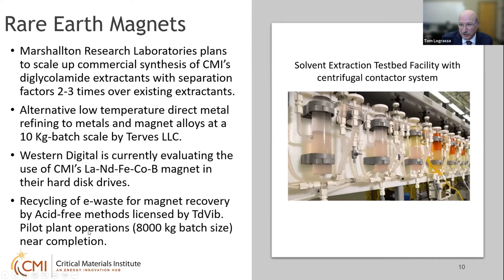And finally, as I mentioned, the acid-free method has actually been licensed by a local company here in Iowa. They're putting the finishing touches on a pilot plant operation, about 8,000 kilogram batch size. So this is taking mostly hard drives, which are crushed and shredded for data security reasons. And this acid-free method, very selective, goes in and just removes the rare earth, anything rare earth dissolves away. It leaves the aluminum, the steel, the precious metals, the plastic, everything else intact, and that can be normally recycled, for the copper, for the steel. So it's a very nice process.